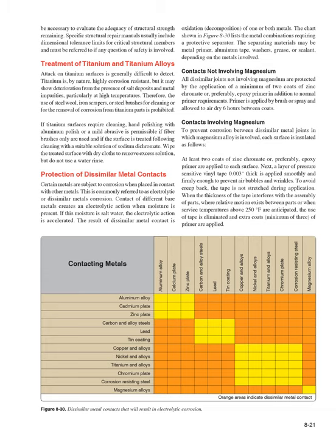Contacts involving magnesium. To prevent corrosion between dissimilar metal joints in which magnesium alloy is involved, each surface is insulated as follows. At least 2 coats of zinc chromate or, preferably, epoxy primer are applied to each surface. Next, a layer of pressure-sensitive vinyl tape 0.003 inches thick is applied smoothly and firmly enough to prevent air bubbles and wrinkles. To avoid creep back, the tape is not stretched during application.